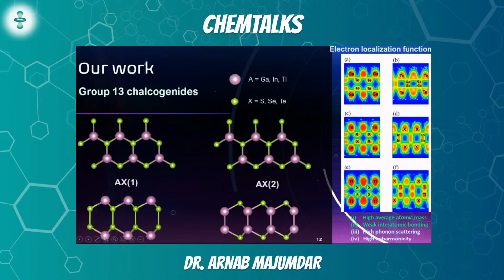This is called the electron localization function. We can just focus on the middle layer, that is the InX layer. It's all same otherwise. For figure C, we can see that the outer planes are occupied by indium and the inner planes are occupied by chalcogen, X. For figure D, it is exactly the opposite. Indium occupies the inner plane and the chalcogens occupy the outer planes. So basically C corresponds to AX1, the structure that we predicted as well as got from the database and have been exploring. And D represents the AX2 structure, which has already been studied extensively in literature.